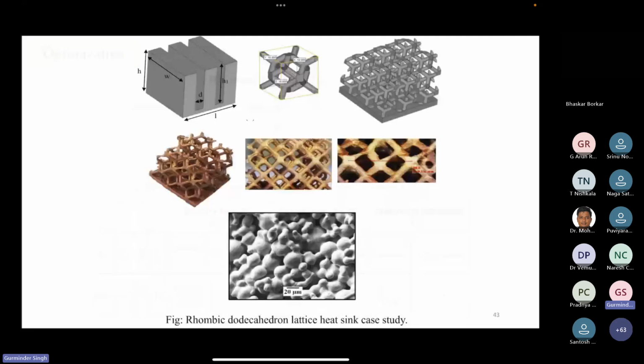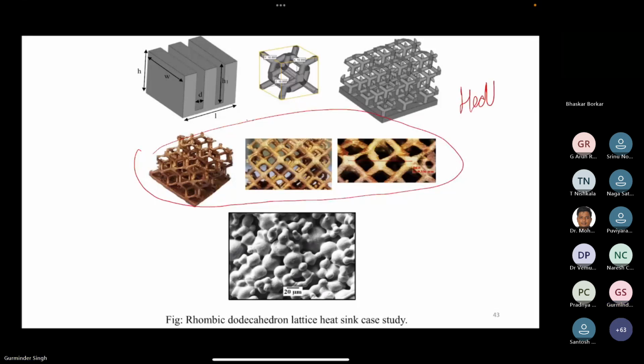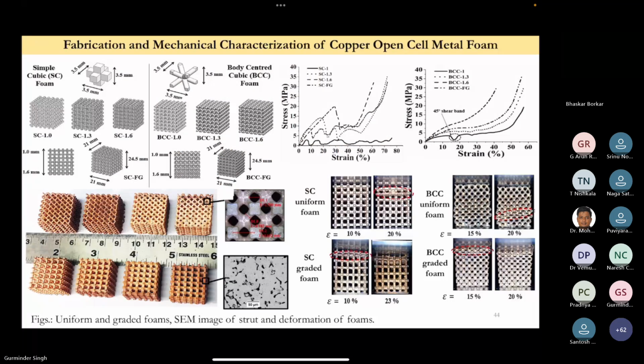So we have done multi-objective optimization and we have tried to fabricate heat sinks. These are heat sinks which we have fabricated with different lattice structures, and also did some heat transfer processes on them to know the pressure drops, because when you are going through a high surface area lattice structure, how can this copper-based 3D printed product be used for better heat transfer. We have also used this process to make complex structures like simple cubic foams and body-centered cubic foams. And I was discussing graded structures, which have a variation in the lattice structures.